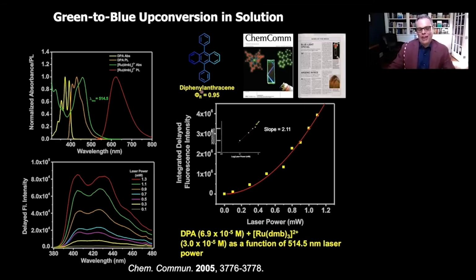So the first thing was anthracene's fluorescence is only 30%. So we immediately figured if we went to diphenylanthracene, if we did everything right, we're going to fluoresce out most of the photons that we can generate through upconversion. And as you can see, between zero and one milliwatt, we were generating, no problem, lots of upconverted photons. Easy to visualize in a cuvette. And this was the one that got recognized by C&E News. And this came at a good time because this was right after I was promoted to associate professor, and I think helped lead me to get promoted to full professor relatively fast.